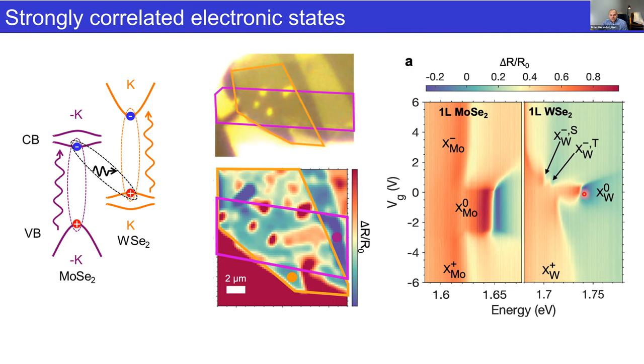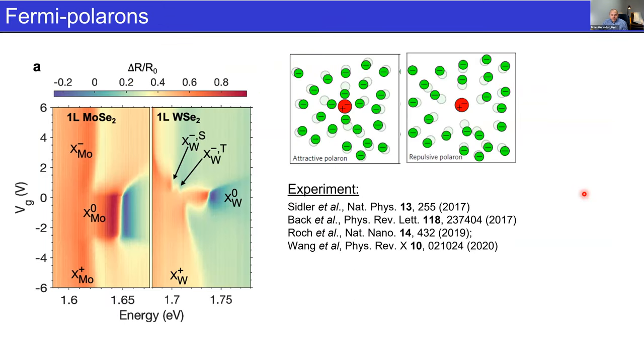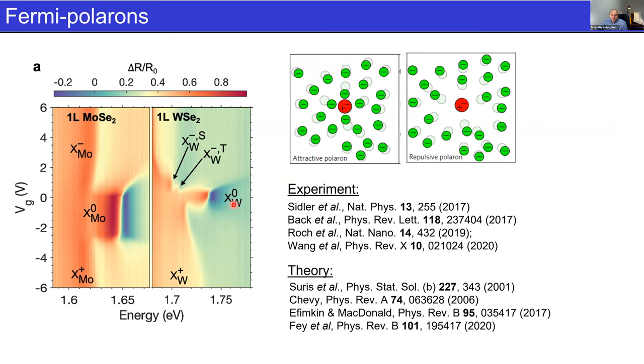And then we have, actually, I think I should go to the next slide. We have signatures of Fermi polarons. So basically, because we have this two-dimensional electron gas, we have our exciton, and it can feel either the attractive or repulsive interactions with the surrounding Fermi sea. And we get these two different types of interactions. So basically, it's akin to a trion and a neutral exciton, although depending on the Fermi energy, the importance of the Fermi sea is a little bit different, in how bound the particle is. So what we see are these different features. They're quite well understood. I won't go into details here.